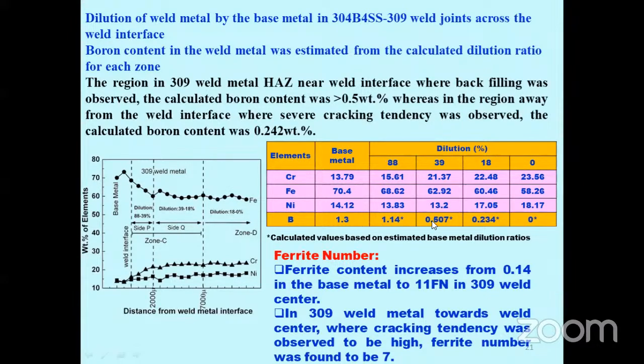Here, the boron content is falling below 0.5 weight percentage, between 0.5 to 0.2 weight percentage boron. And this region is very vulnerable to cracking, as we saw earlier in the literature, that any boron-containing stainless steel containing less than 0.5 weight percentage of boron is prone to hot cracking. So this is also in line with this.